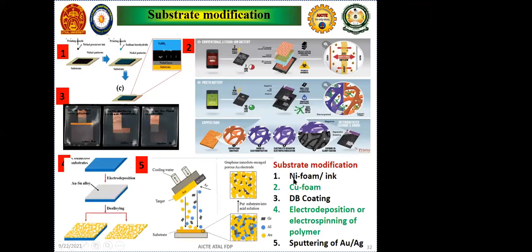As I said already, the major factor for developing the anode free battery is the current collector. How can we do interface engineering to develop the current collector, or how can we use the current collector in a proper way to tackle the shortage of lithium, or to handle charge discharge without getting dead lithium or dendrite formation? So what exactly can be done with the current collector to make it anode free? Many people use different strategies. When they use copper as the current collector, they have changed it to a copper form, so that it can capture a lot of lithium during charge discharge, and then the anode will be developed when it is an anode free battery. So the anode will be formed when the charge discharge happens in a copper form.